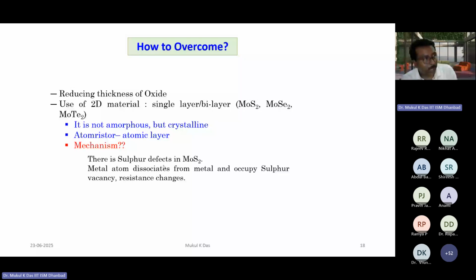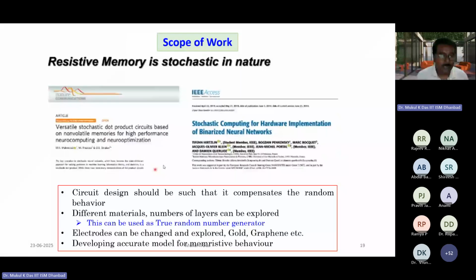When you put MoS2 with sulfur defects between two metal layers and apply some voltage, a metal atom may migrate from the metallic electrode to a sulfur defect, which is a vacancy. If a metal atom migrates from the electrode to that sulfur defect, it will change the resistance. This is the main mechanism of changing resistance in a 2D material. It will be described in more detail. Now let us see what type of works have been obtained in different papers.